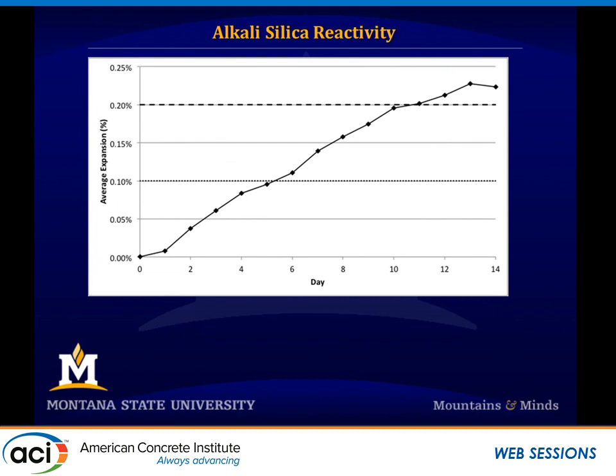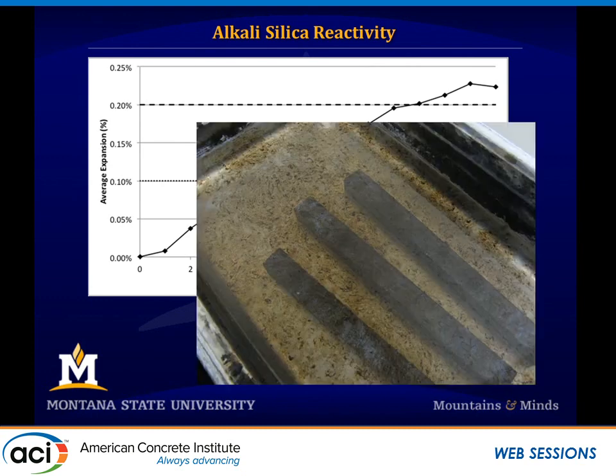Alkali silica reactivity, in terms of durability. Our data showed that it could potentially be an issue, but we found the problem to be that this is filled with asphalt pavement, right? So you have a tar coating on everything. The test procedure that we used involved heating these bars up to 180 degrees, and when you heat tar up to 180 degrees, it changes its properties and it expands. And that's what we're trying to test with ASR, is the expansion.